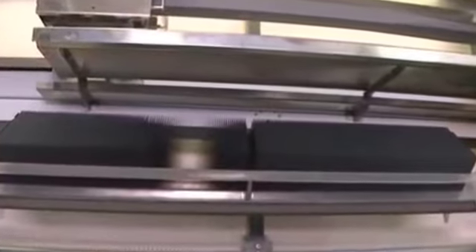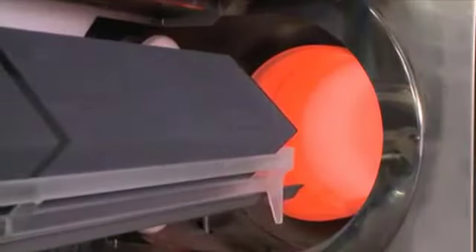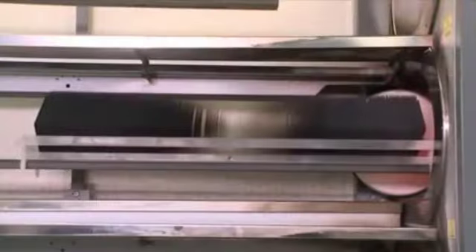In a further processing step, a negatively charged coating is applied to the positively charged wafers in a diffusion furnace at temperatures ranging from 800 to 900 degrees using phosphorus gas. The phosphorus atoms diffuse into the wafer surface, and, as a result of such doping, the surface changes from positive to negative.